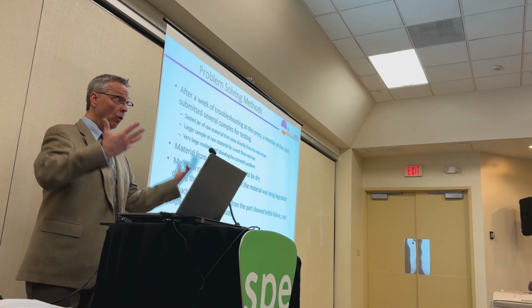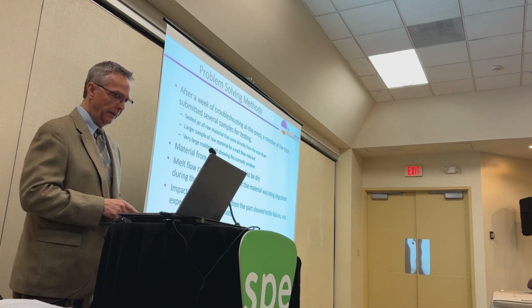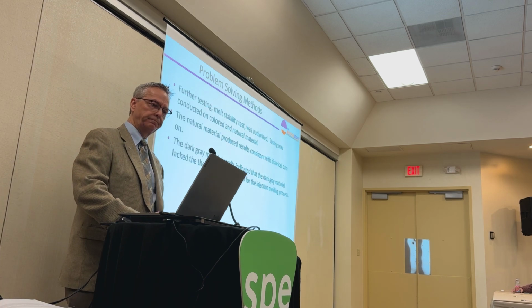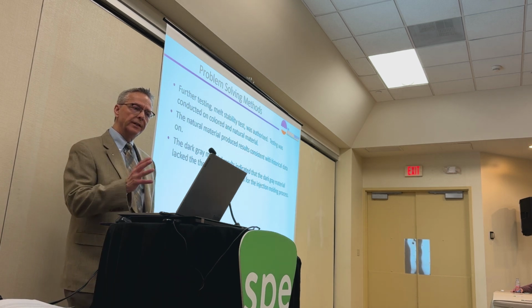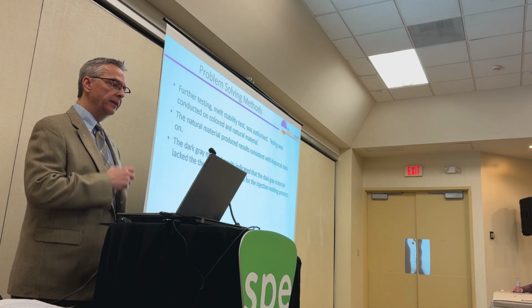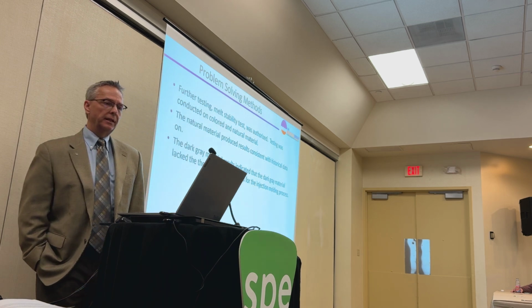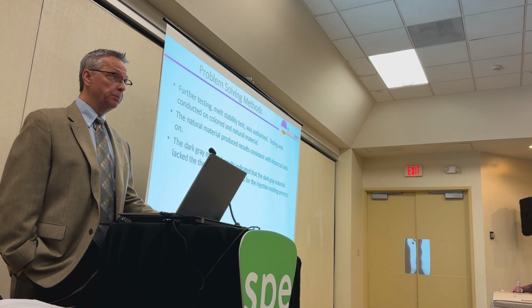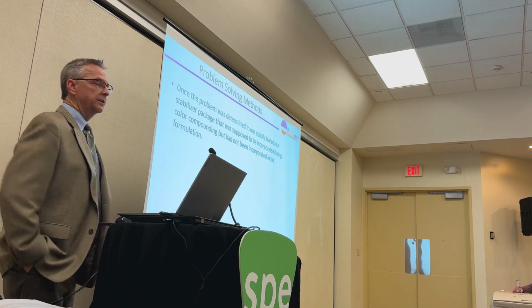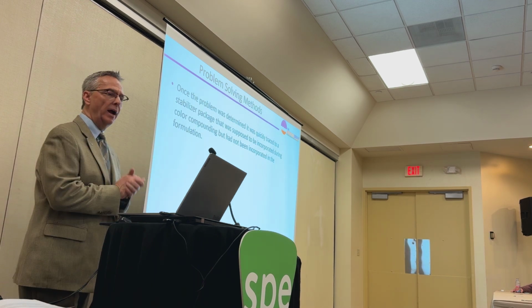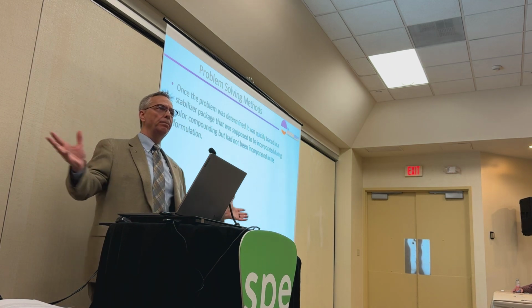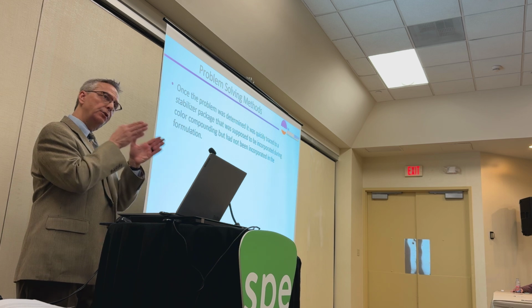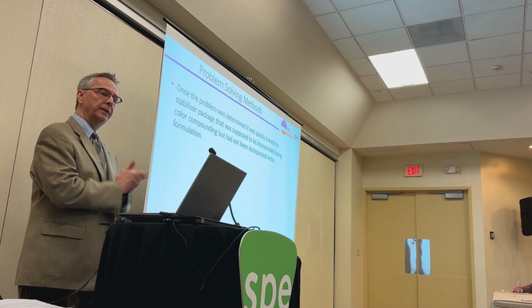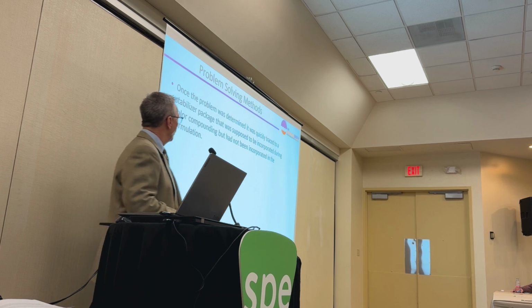Impact testing showed that polycarbonate, normally a very ductile material, was behaving in a brittle manner, which is consistent with that molecular degradation. They did one more test, a melt stability test, performed on various samples that were colored and natural. And what they found was that the dark gray material results indicated that the material lacked the thermal stability for the injection molding process. It was supposed to have some additives in there. Once all that testing was done, and it wasn't a whole lot of testing, it was very practical testing. That's one thing about Mike. Mike didn't like jumping into a whole lot of testing. He had a focus: let's do the right tests, get them done, and see what that data tells us.